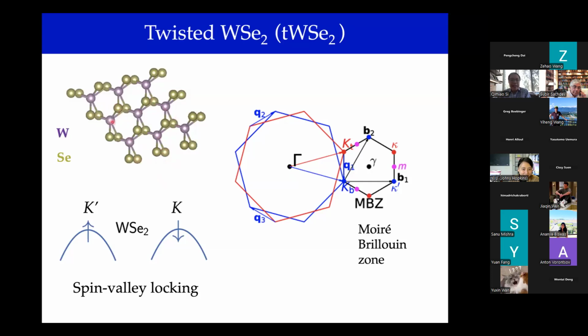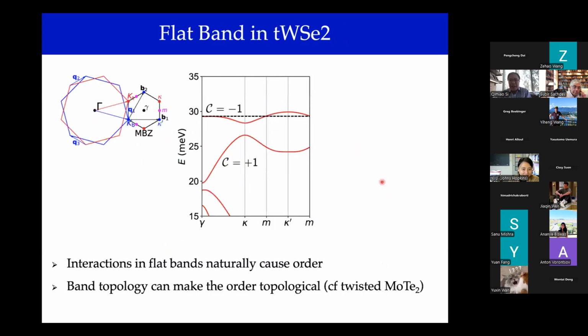So instead of graphene, one looks at, in this case, WSe2 with the lattice that's seen here. The single layer of WSe2 already breaks inversion symmetry. There's a strong spin-orbit coupling that actually simplifies the degrees of freedom. The valley and the spin turn out to be locked together, and one puts 2 layers of this, twists them, and forms the familiar moiré structure with the reduced moiré Brillouin zone. And the interaction happens here. And generically, there's a flat band. And one could realize something like a half filling of the flat band.